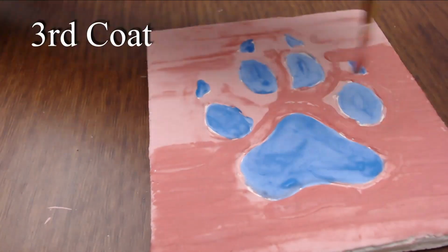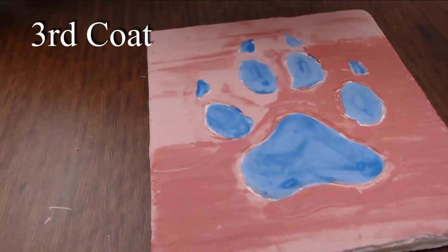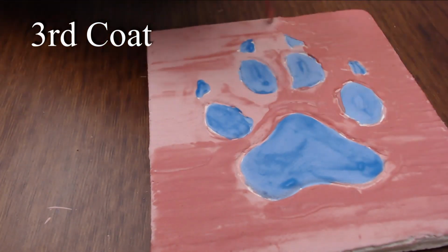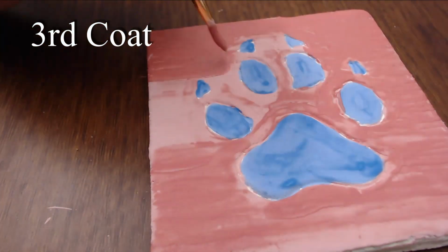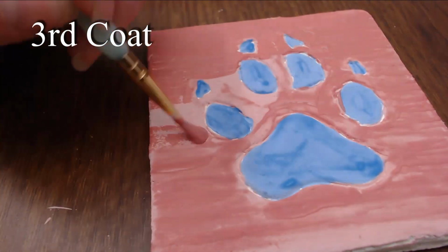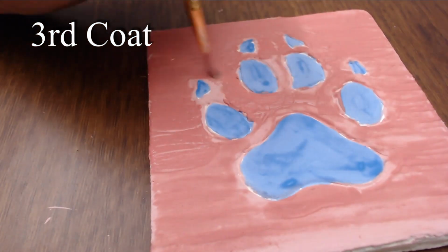Make sure that the glaze does not get on the sides or bottom of the tile, as this will fuse or stick the tile to the kiln shelf and would most likely break when removed.